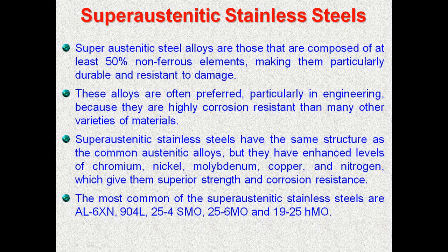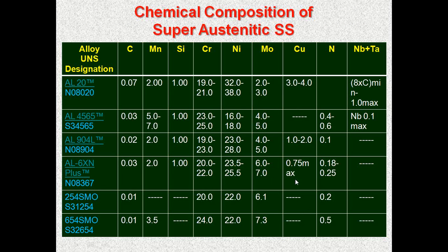And they have the same structure as the austenitic stainless steels, but as I told, they have very high chromium, nickel, molybdenum, copper, nitrogen, and so on. The most common types of them are the AL6XN, 904L, 254 SMO, 25-6MO, and 1925hMo. You can see their composition here. The nickel is very high, chromium is also very high, molybdenum is there at nearly 5-6% up to that maximum. And the copper is there in some alloys, and also nitrogen. And this combination of very high alloying elements makes them super austenitic. That means a very stable and highly corrosion resistant variety for selective applications.